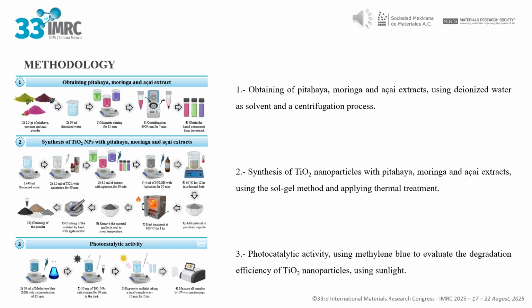Methodology. 1. Obtaining of pitahaya, moringa and acai extracts, using deionized water as solvent and a centrifugation process. 2. Synthesis of TiO2 nanoparticles with pitahaya, moringa and acai extracts, using the Sol-Gel method and applying thermal treatment. 3. Photocatalytic activity, using methylene blue to evaluate the degradation efficiency of TiO2 nanoparticles, using sunlight.